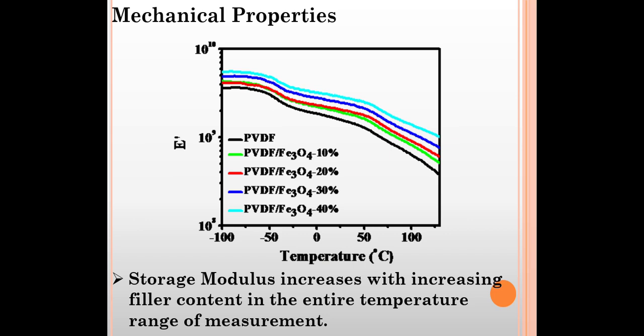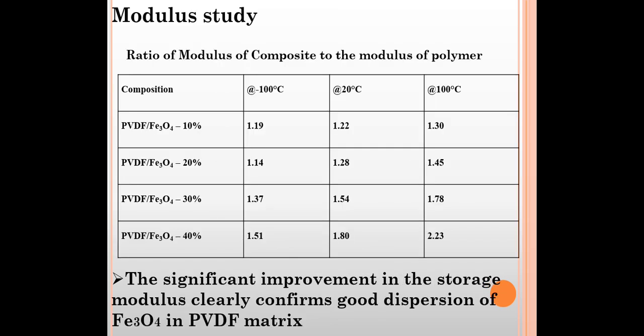The figure shows the storage modulus as a function of temperature. The temperature is in the range of -100 to 150 degrees Celsius. From this figure, we clearly see that the storage modulus increases in the entire temperature range with the addition of nanofiller. If we compare different particle loadings, it shows that the storage modulus increases with increasing filler loading. Therefore, we conclude the uniform dispersion of the Fe3O4 nanoparticle in the polymer matrix.